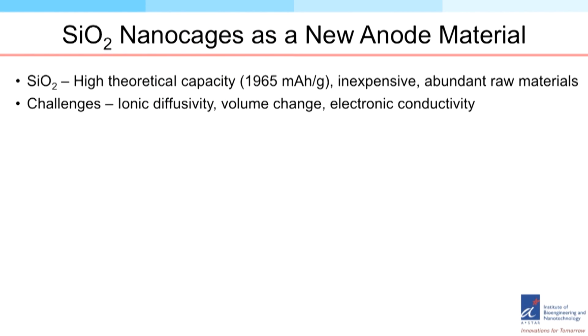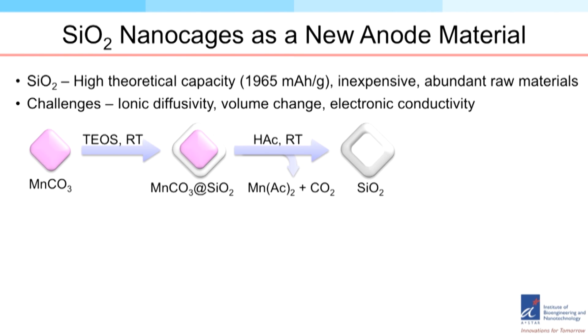To have better electronic conductivity, we make use of a nanocomposite — first creating a nanometer-sized material with walls of about 15 nanometers. We use a template synthesis: we start with a manganese carbonate nanocube as a template, coat it with silica, and then remove the internal manganese carbonate part, leaving behind cages. These nano walls are about 15 to 20 nanometers.